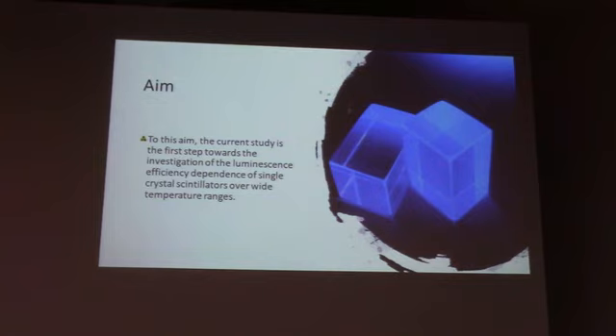So how do we study that? How do we make the research? We take the crystal, we increase the temperature pretty high, and then we measure the light that is produced when this crystal is irradiated by X-rays or any other radiation, but in this project we used X-rays. So we measure how much light comes out of it. So we measure the light at room temperature, and then we increase the temperature and see how the absolute efficiency, which is actually the amount of light that is coming out of the crystal, is changing.